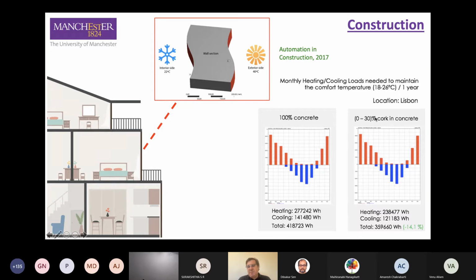And as you can see, when we move from a traditional wall made in concrete to walls with a gradient structure, maximum of 30% of cork, it was possible to achieve a 14% reduction in terms of energy consumption. So besides the sustainability issues, this approach allows us also to reduce energy consumption.